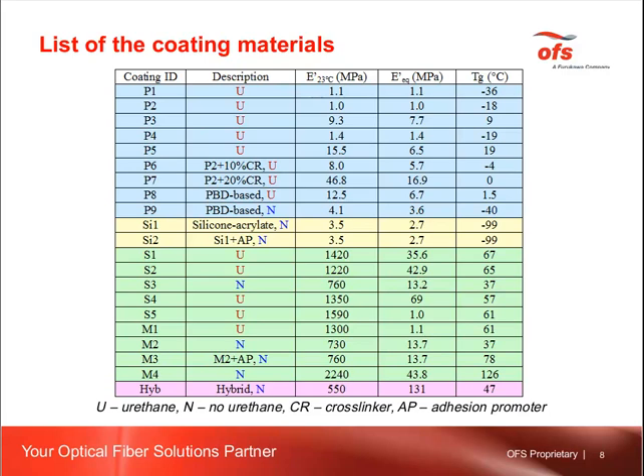Primary coatings P8 and P9 were formulated ourselves. For this, we used two different polybutadiene-based oligomers, one with urethane and the other without urethane. These are the only coatings that we formulated ourselves. Also, in two cases, we added an adhesion promoter. So we added it to a silicone coating Si2, and we added to a monocoat M3.